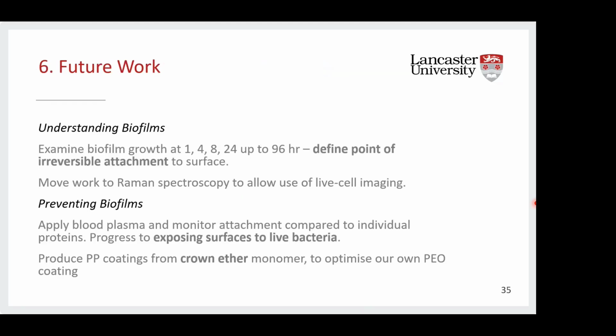So what are the next steps in our experimental research? Well, in terms of understanding biofilms, we're going to start examining the biofilm growth from 1 hour post-incubation up to 96 hours. What we're trying to do is define this point of irreversible attachment to the surface, so that point at which the matrix is forming. Then we're also going to be moving away from FTIR and onto Raman spectroscopy, and this is going to allow live cell imaging. With Raman spectroscopy, you can actually have your samples incubating and collect spectra at the same time, so you can monitor the growth in real time.